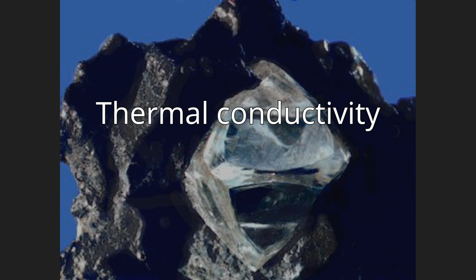Thermal conductivity. Unlike most electrical insulators, diamond is a good conductor of heat because of the strong covalent bonding and low phonon scattering. Thermal conductivity of natural diamond was measured to be about 2200 W/m*K, which is 5 times more than silver, the most thermally conductive metal. Monocrystalline synthetic diamond enriched to 99.9% in the isotope 12C had the highest thermal conductivity of any known solid at room temperature, 3320 W/m*K, though reports exist of superior thermal conductivity in both carbon nanotubes and graphene.